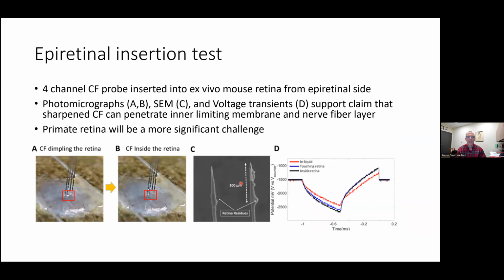More evidence for that is the biological material we saw afterwards on the carbon fiber electrodes, as well as the change in the voltage transient. So in the liquid, for a given current, we developed this voltage, shown in red. But once we were touching the retina or inside the retina, the voltage increased. So that indicates that we have a higher resistance to current flow, which would be the case because the resistivity of the retina is higher than the surrounding liquid. So altogether, this indicates that at least 4 carbon fibers can penetrate into the retina.